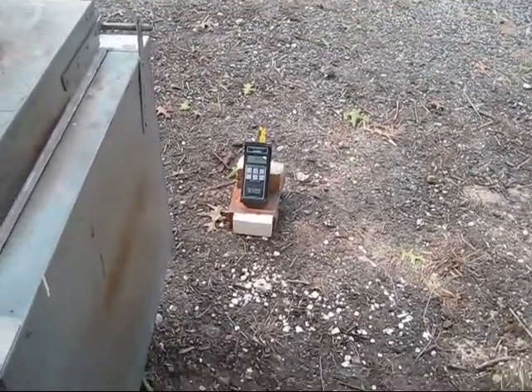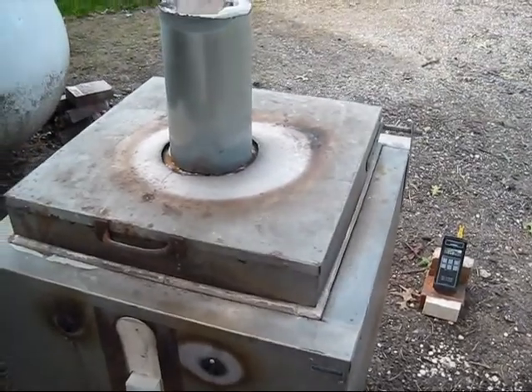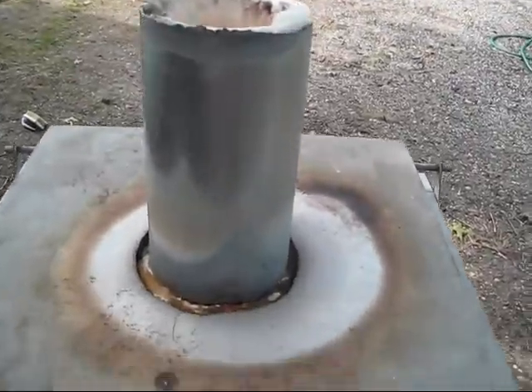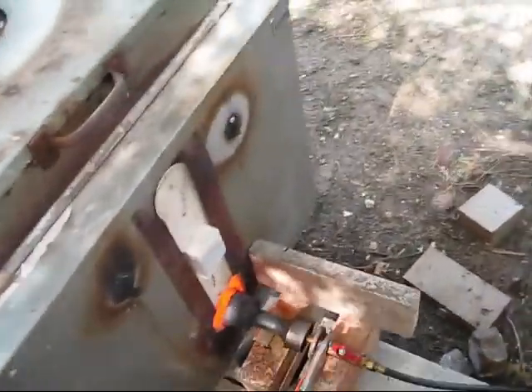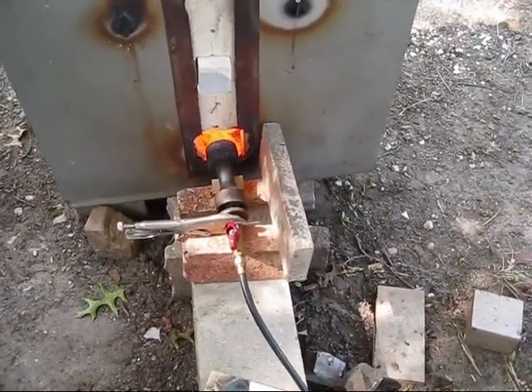What I'm going to do is wait for it to get to 2300 degrees, and I'm going to force it into reduction. I have a little piece of old kiln shelf here I'm going to stick on top of the chimney. And then I'm going to up the pressure probably to two to see how the reduction will start. I'm going to have a nice long reduction.